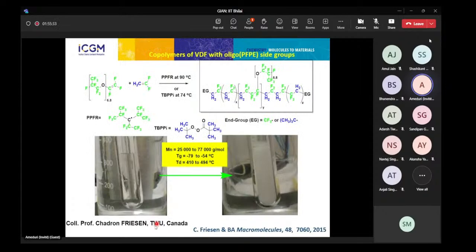Also, collaboration with Professor Chad Friesen in Canada. He came for sabbatical, and Chad told me, "Oh, we have prepared some oligomers containing some trifluorovinyl group." Wow, this is very interesting because we can copolymerize with VDF. And this is what we did. We didn't have so much amount, about 8 to 10 grams. So we decided to make about Carius tubes with 1 gram of VDF and let's say 100 or 200 milligrams of compounds here, because this is heavy.